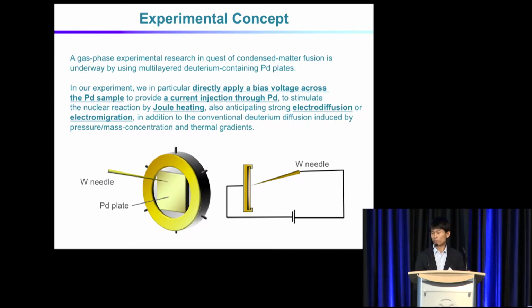The main feature of our facility is a gas phase chamber with a bulk palladium plate which is loaded with deuterium gas, and then we directly apply bias voltage across the thickness of the palladium sample, and make a current injection through the plate so that we can stimulate the reaction by Joule heating as well as by electrodiffusion or migration. In particular, we cap one side of the plate with gold film as a diffusion barrier to induce a one-sided diffusion of deuterium atoms for the simplicity of our analysis.